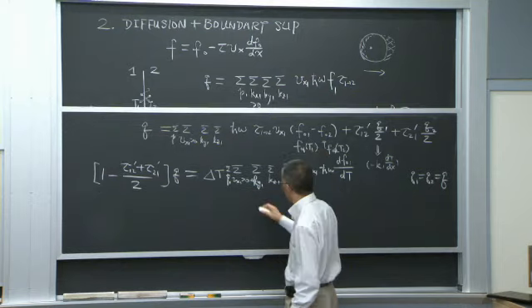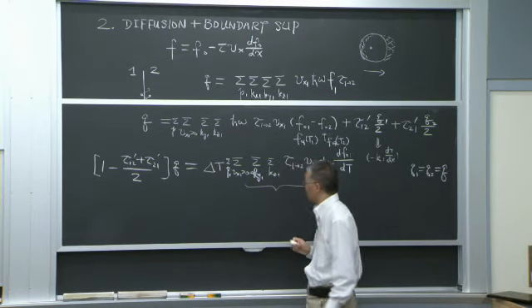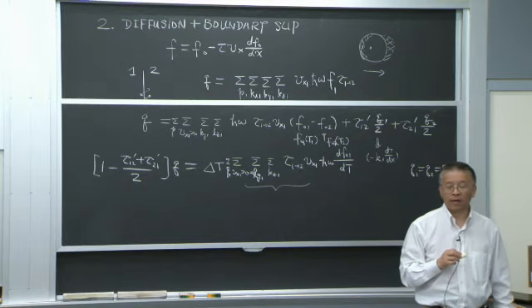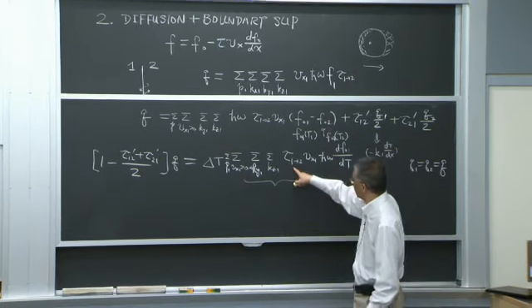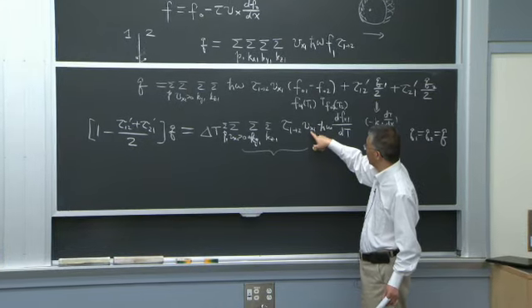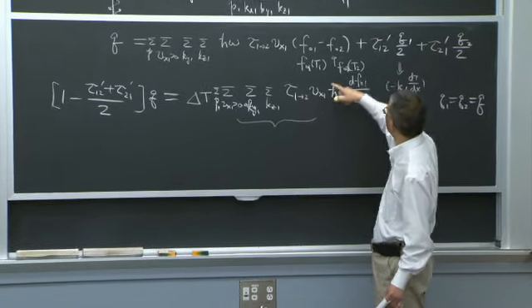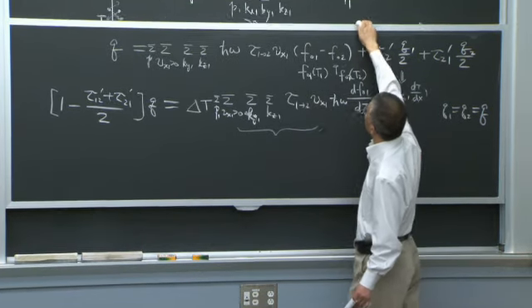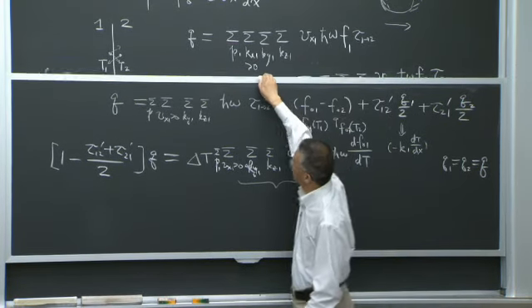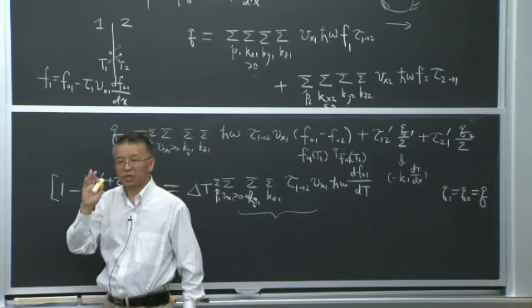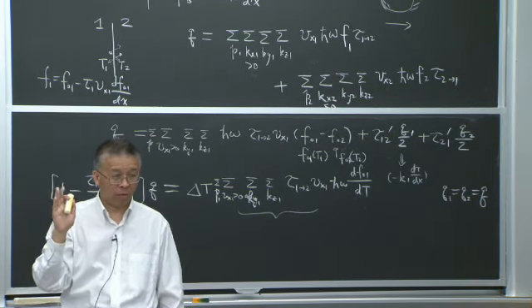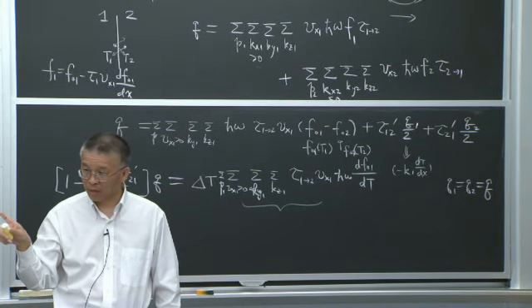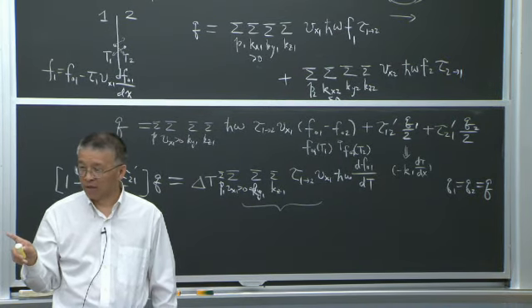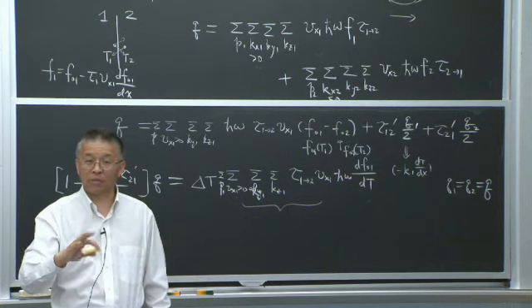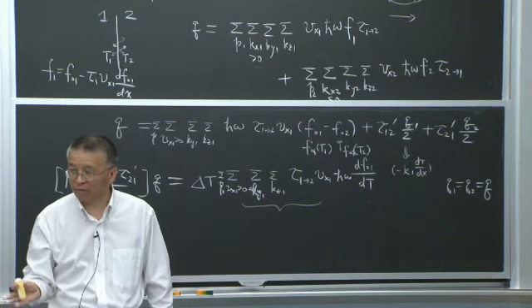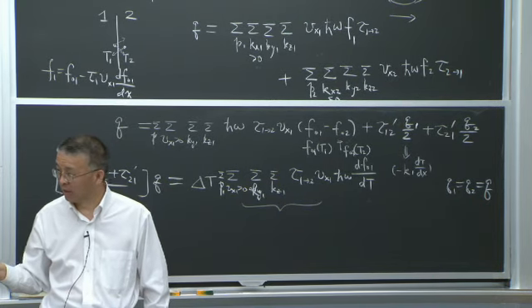And of course, this one, you can again convert your summation into integration, and in this conversion there's a slight difference. This is tau 1 to 2. Here I have VX1, right? Here, when I do Q, I have VX1, but F1 has another tau VX1. So that's a VX1 squared in the Q. VX1 squared has sine squared theta, while VX1 is just sine theta. So my averaging for this transmittance is actually slightly different than the angle weighting, right?